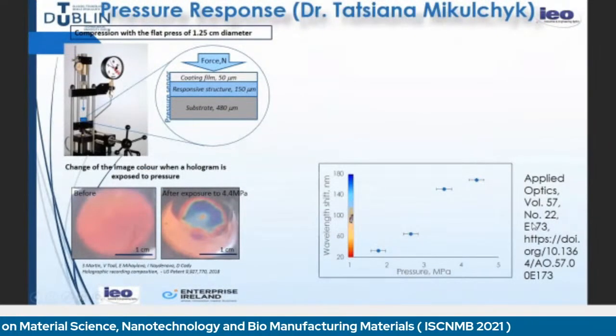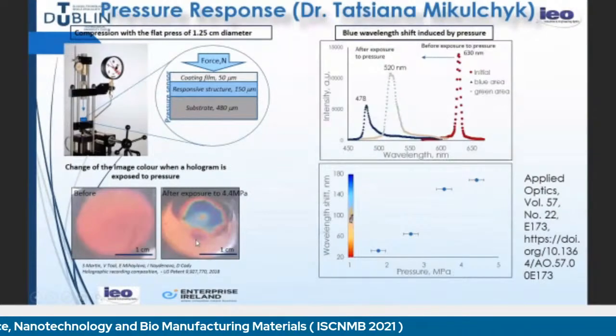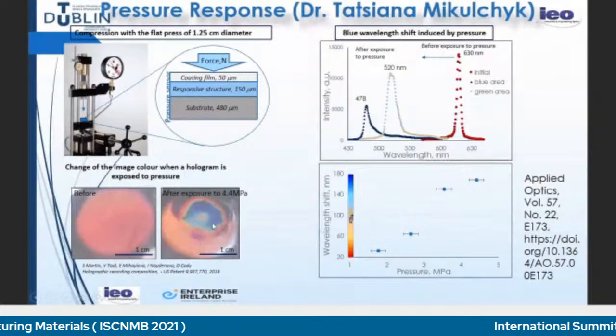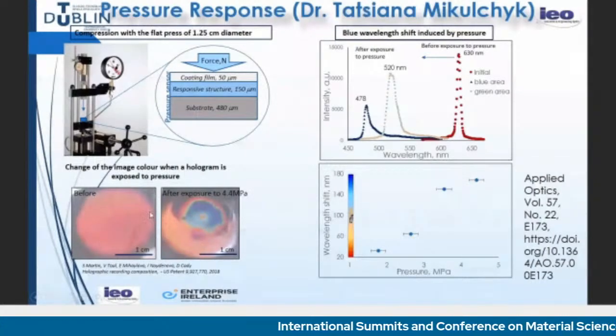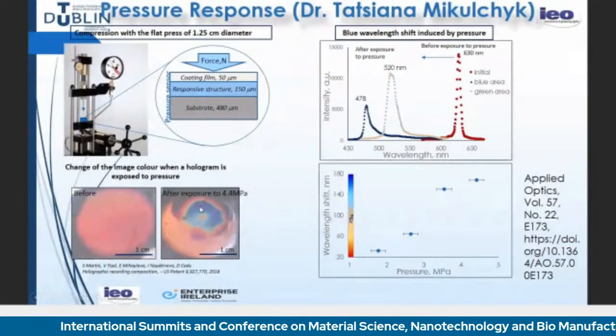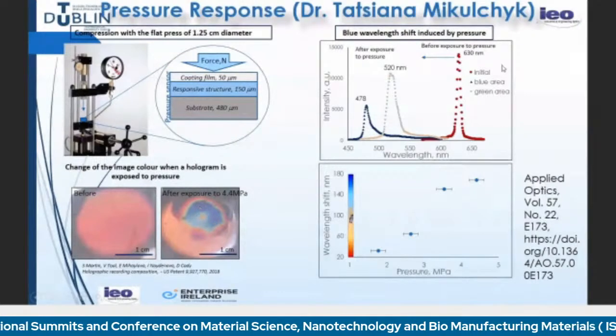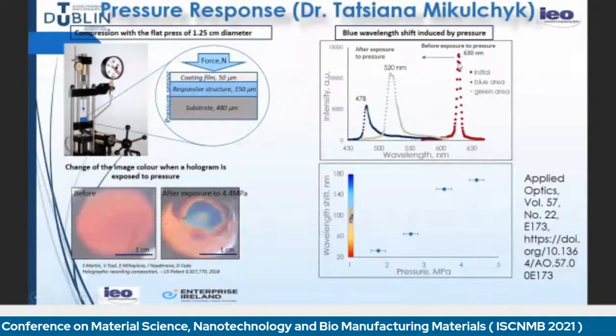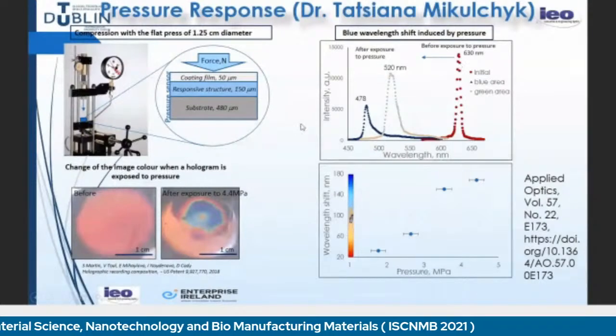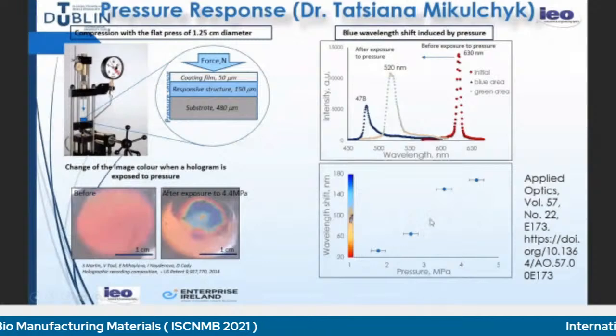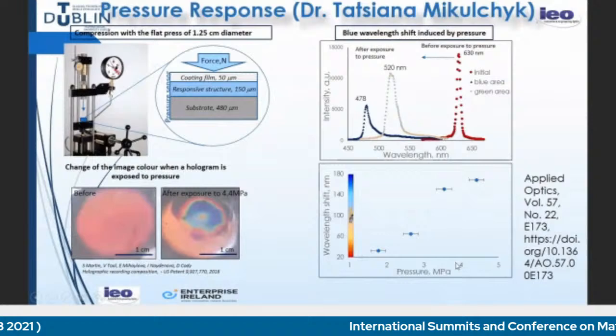This is the hologram before and after application of pressure, which is a challenge actually, to apply a uniform pressure on the material, something that we are still working on, but it definitely gives you a map of the applied pressure in color. And we have also measured spectroscopically the response at the different areas, the blue, the green, and the red area, and the wavelength shift was studied as a function of the applied pressure.